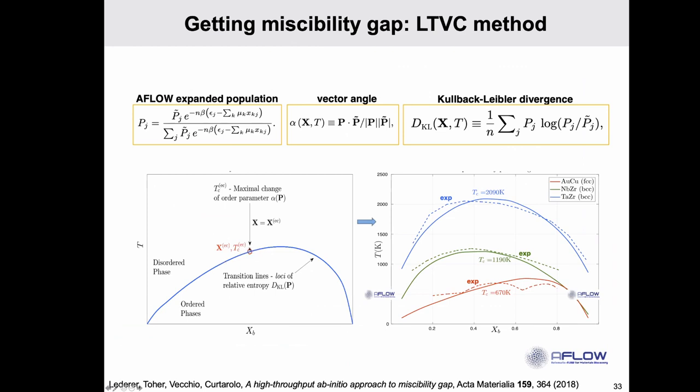But at this point, before or after, we know that we change all the occupancy of these states. All these P's have changed dramatically, going a little bit above and a little bit below, okay? Because the angle changed a lot. So we get all this probability above and all this probability below, and through the Kullback-Leibler divergence, which is a measure of the relative entropy that has been lost in the system. If this is order, there is no entropy, ideally perfectly ordered, no entropy; perfectly disordered, it's all entropy. And then the amount of entropy that is lost, this divided by this, is a relative entropy loss going down, or gain going up. And this is the Kullback-Leibler divergence that has been known for many years.